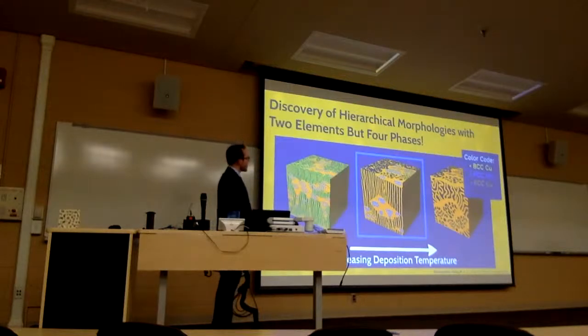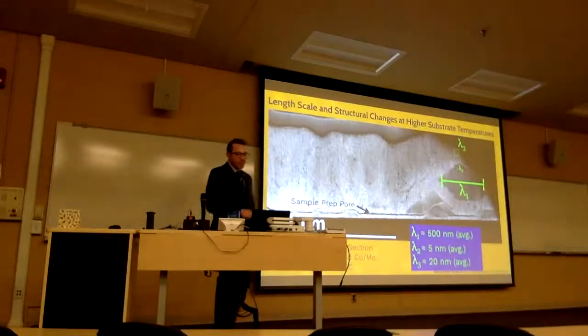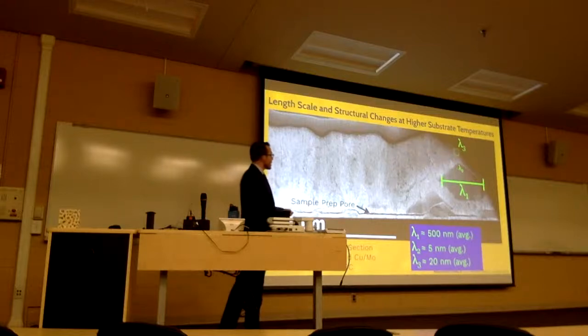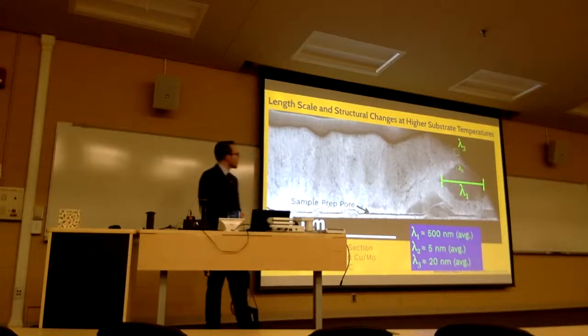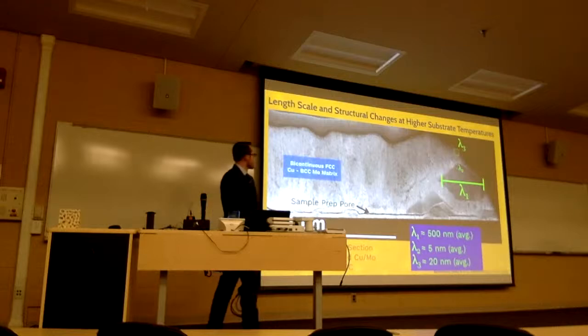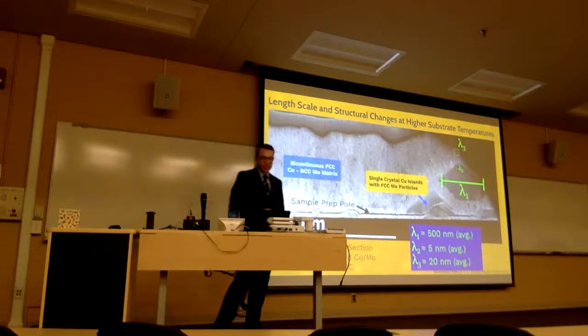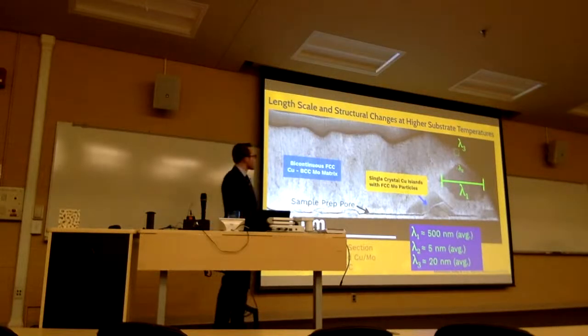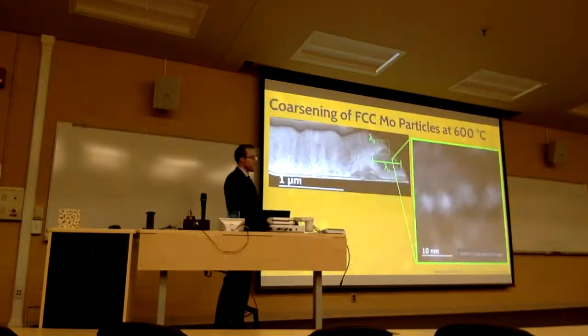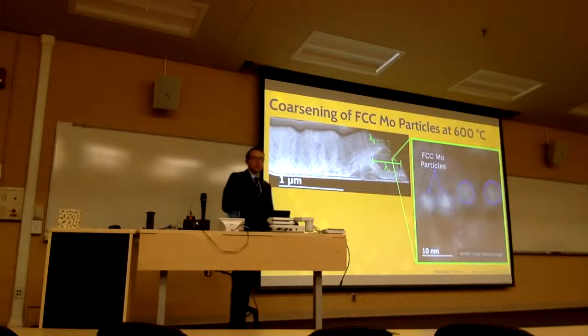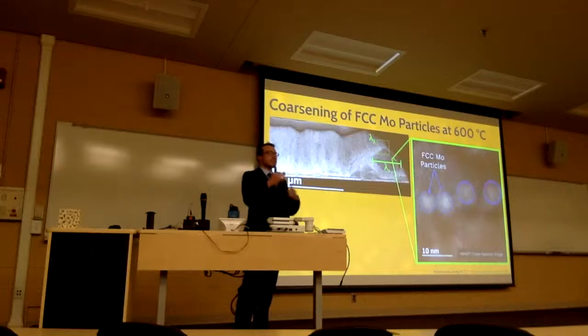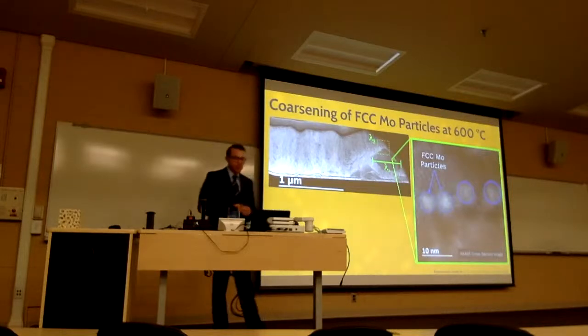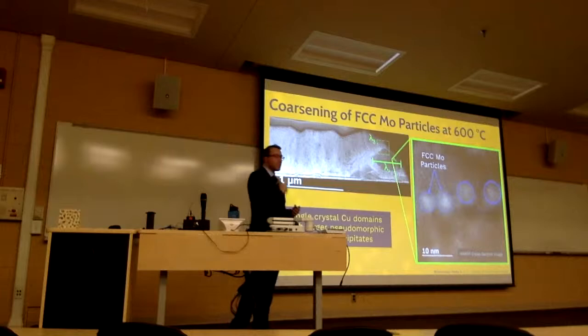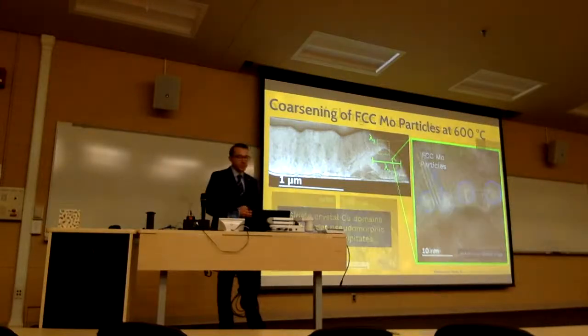At slightly higher temperature, we actually coarsen the structure quite considerably. You can see lambda 1, these lambda values have increased. If we look inside of those islands, we still have a bicontinuous matrix with single crystal islands scattered throughout. If we look inside that island, we can actually see again those FCC moly particles scattered within that copper-rich island. You can see that they've lost some ordering inside that copper-rich island. So what we have is larger pseudomorphic FCC moly precipitates.